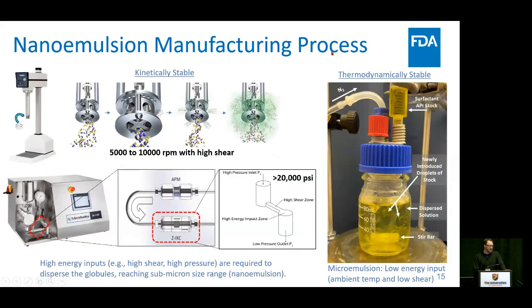So in order to overcome that kind of immense interfacial energy, usually for nanoemulsions, you're using these really high energy processes. So that's either homogenization or in a lot of cases, microfluidization. And so this is using a high energy input, high shear, to reduce that particle size so that there's sufficient enough surfactant to cover that oil surface and stabilize those particles. This is in contrast to a thermodynamically stable system like a microemulsion, where you can actually make these at really low energy inputs at like ambient temperature with very low shear conditions. And basically what you're looking at is the surfactant and API solubilizing and dispersing into the carrier.